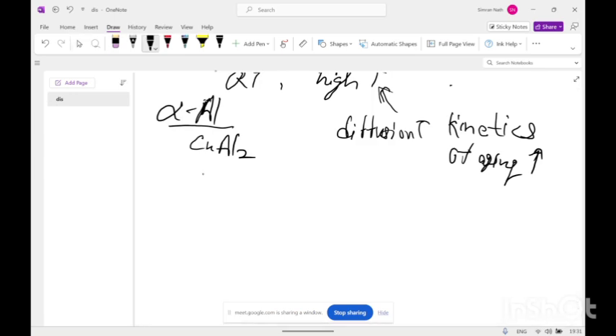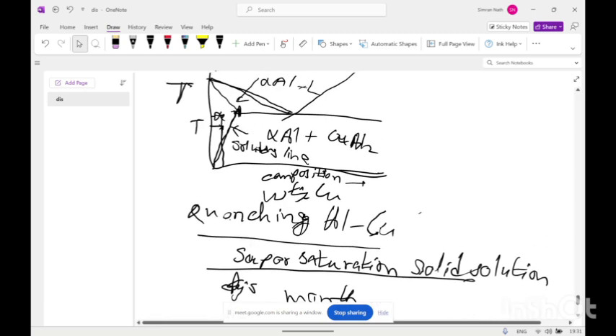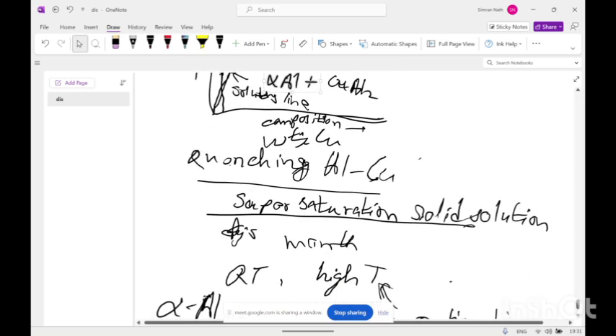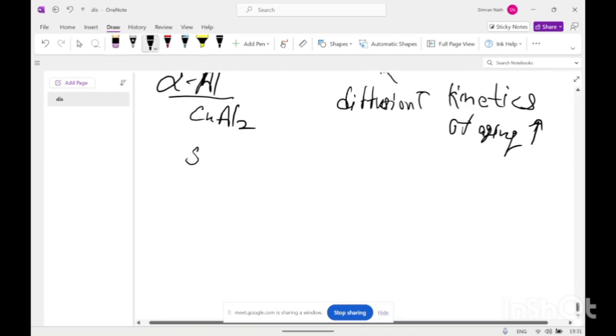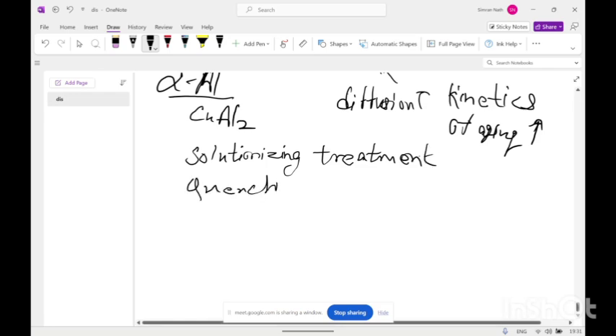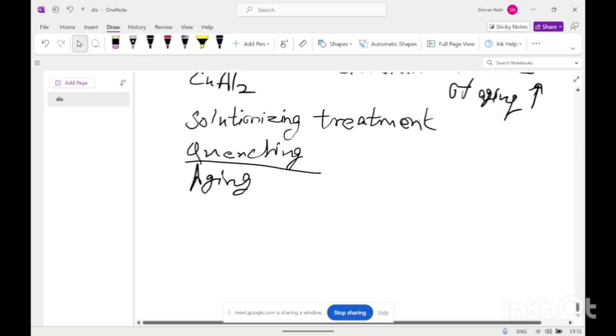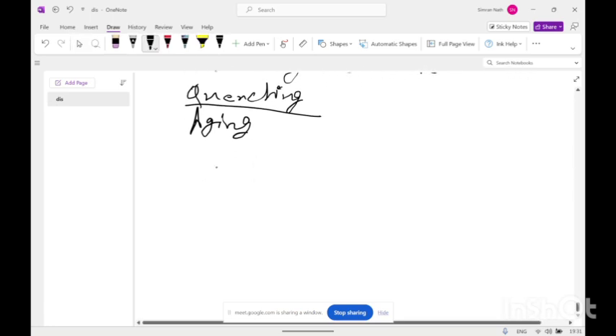The treatment of heating this composition to the single phase region is called the solutionizing treatment. Next is quenching and aging. So why is quenching done from the single phase solid solution region? Because in quenching a high cooling rate is provided that entraps the copper atoms.